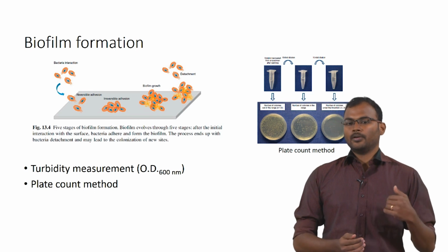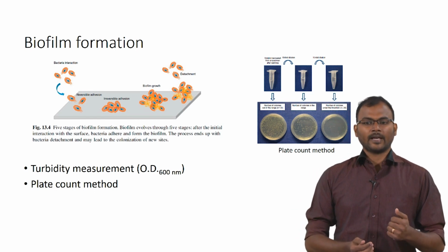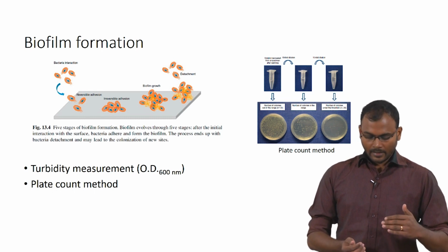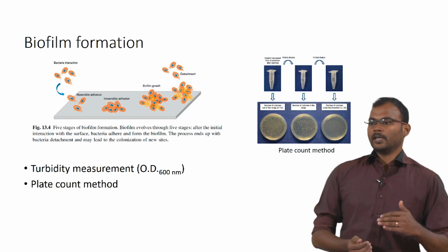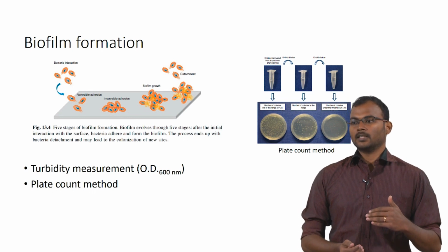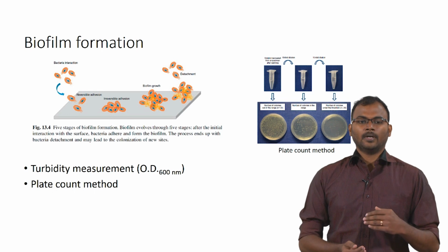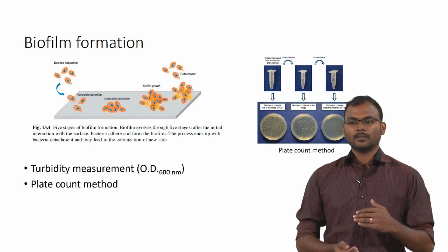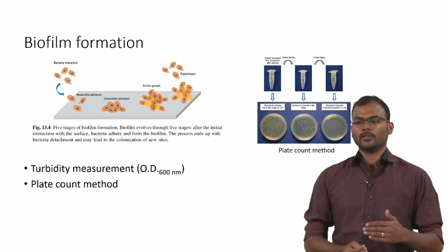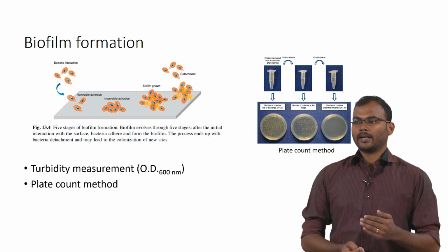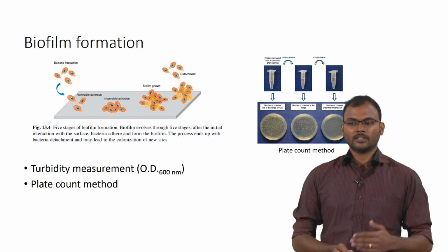You inoculate the control with the bacteria and inoculate your sample with the bacteria, and after a particular amount of time when the bacteria reaches its log phase, you check how much of the bacteria has adhered onto the material surface. From that, we wash out the bacteria adhered onto the surfaces and estimate using a UV visible spectrophotometer.